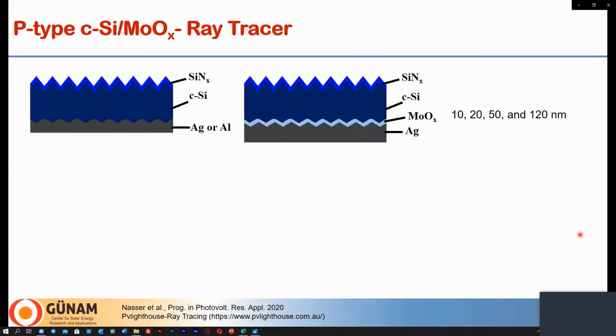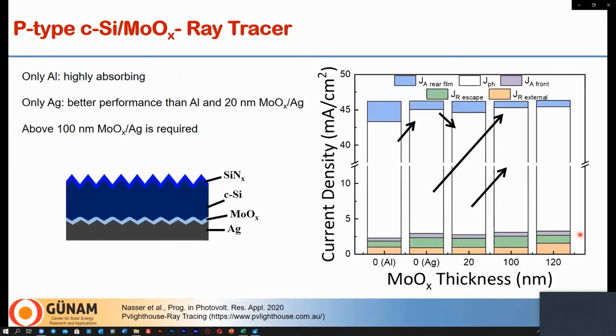The front side is similar to the fabricated P-type silicon molybdenum oxide cell, and the rear side features molybdenum oxide with different thicknesses ranging from 10 to 120. Also, we have simulated reference solar cells with silver or aluminum. Aluminum is just to show the aluminum back surface field. This is the simulated current density, either photo-generated, this one, or the current that's being lost at each interface. But here we are interested in the one on the front side where our molybdenum oxide silver are. So this is for aluminum back surface field. This is for the solar cell that we produce, and this is for molybdenum oxide with different thicknesses, of course, with silver here.